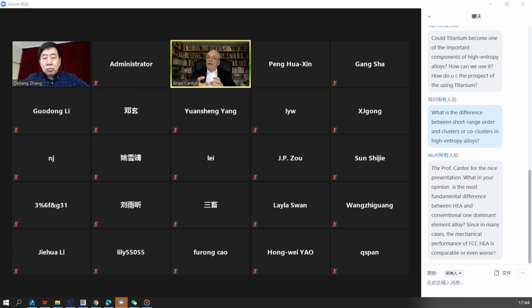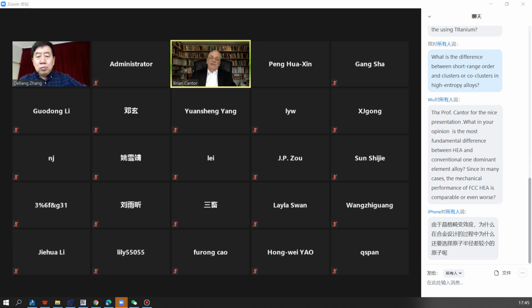We've only in the last couple of years really understood the Cantor alloy itself, and that's the one alloy that's been studied really a lot. People are beginning now to study these other compositions in more detail. But I think we can expect that, depending which composition you change and depending which kind of short-range order you get, you will in some cases move to more wavy slip. It'll be those cases where the stacking fault energy becomes higher, so that you prevent the partial separations, and those cases where the short-range order becomes more effective too. So I think we know what's likely to happen, but we need to do the studies because it won't be exactly the same as we expect.